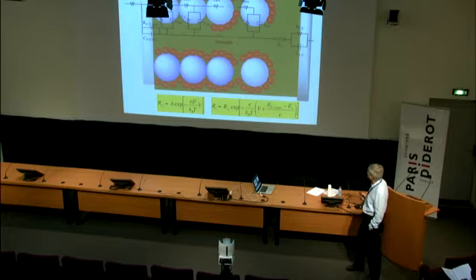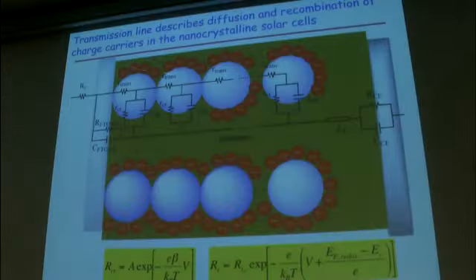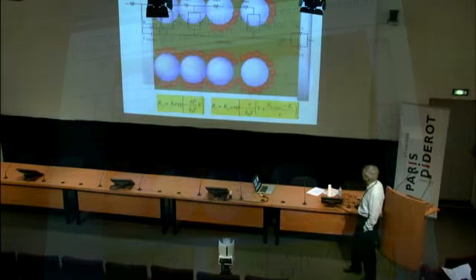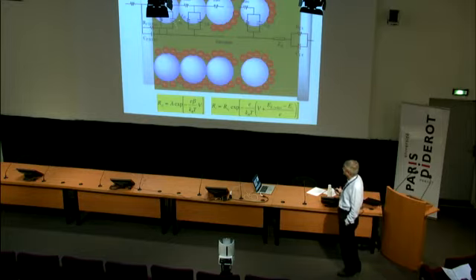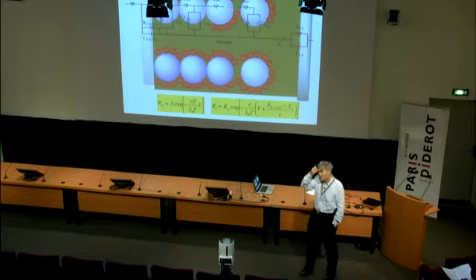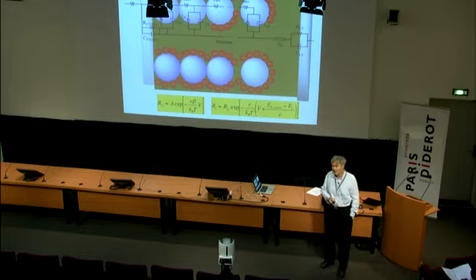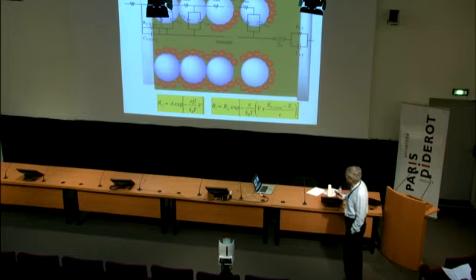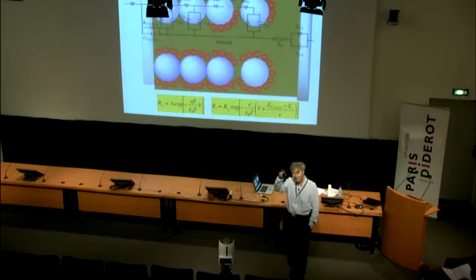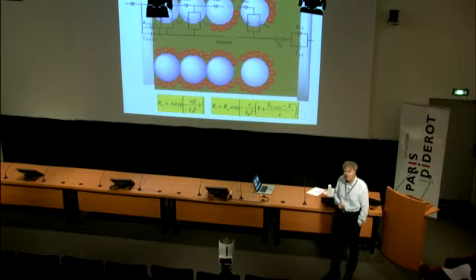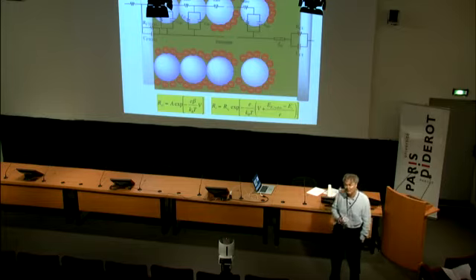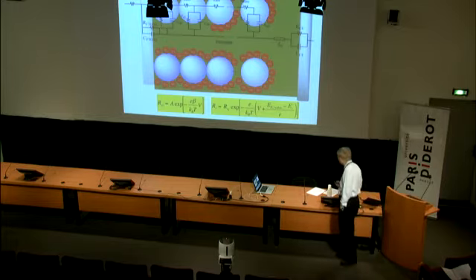We can also use a transmission line description of the diffusion and recombination of charge carriers in these. I'll get to that later, where the key parameters are the transport resistance and the recombination resistance, and they both couple to what is called the chemical capacitance. I won't go into details. Juan Bisquert has been one of the pioneers, our Spanish colleague, who developed all of this. But let me tell you, the ratio of transport over recombination resistance is equal to the ratio of these two time parameters, the transport and recombination time. So if we know the ratio of these two resistances, we know the ratio of these two time parameters, which I mentioned to be so crucial for the operation of that device.